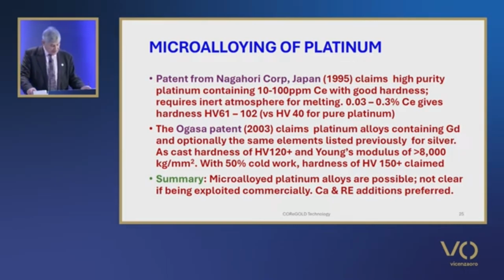The Ogasa patent that I mentioned earlier also includes platinum materials, and this claims platinum alloys of at least 85% platinum containing gadolinium and the other optional elements listed above for silver, preferably calcium, in the range 50 to 15,000 parts per million in total. Cast hardness values of at least 120 Vickers and Young's modulus of not less than 8,000 kilograms per square millimetre are claimed. With 50% cold work, hardnesses of at least 150 are claimed.